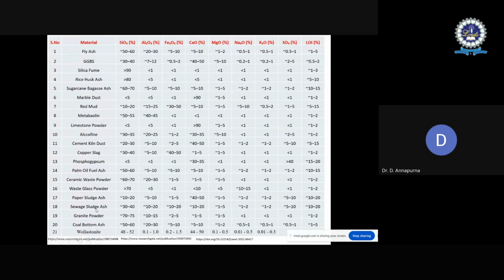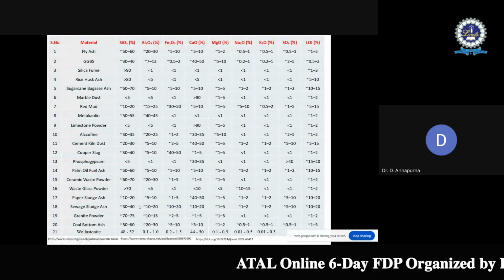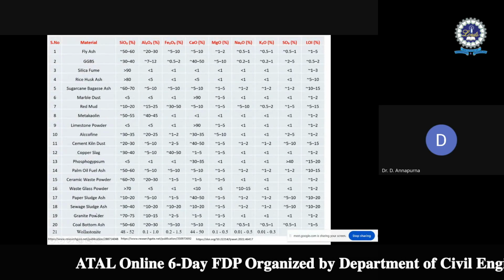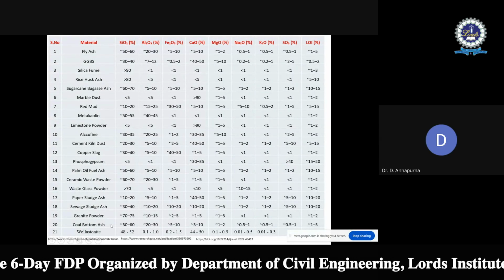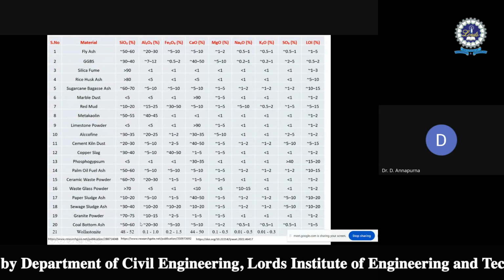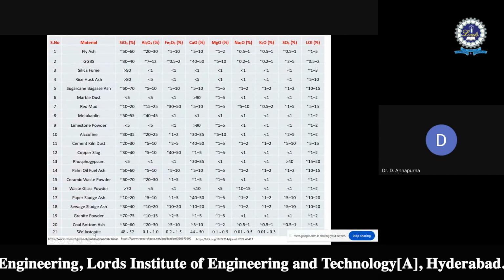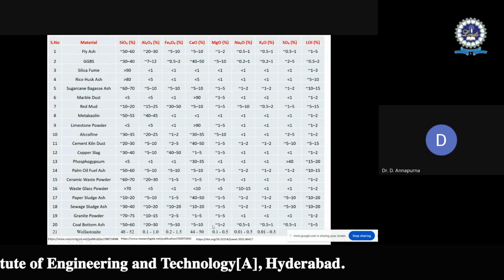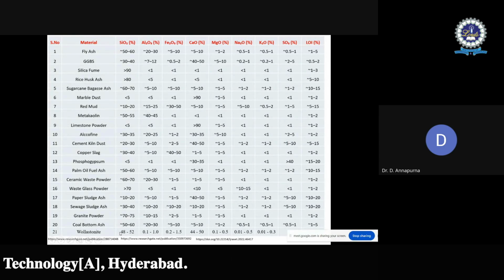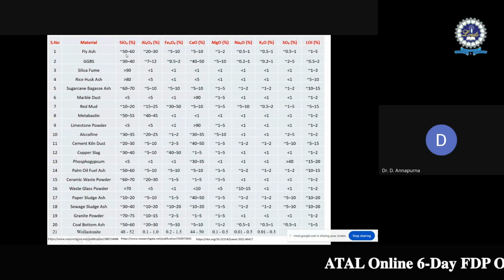Then sewage sludge ash is rich in silica and alumina. It has a good content of silica and alumina. And the granite powder, then the coal bottom ash, is also rich in silica and alumina. Then wollastonite has a rich amount of calcium oxide and also silica. So like that, all these materials have silica, aluminate, and calcium oxide.